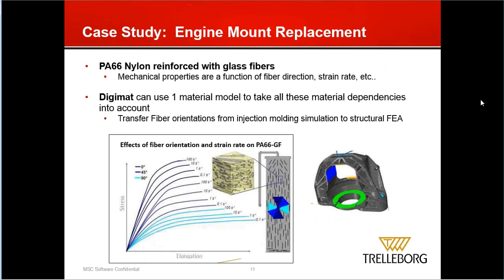The material they chose for that analysis is a PA66 nylon reinforced with glass fibers. And you can see from the chart below that this is quite a complex material to deal with. From the three different colors of curves, or three different groups of curves, you see that the material has a variety of stiffnesses and strengths depending on what the local fiber orientation is. In addition, you can see from inside each one of those groups that the faster you pull on that material, the more stiff it's going to behave, which means that it has a strain rate dependence. So this is a relatively complex material to deal with, and so they decided to use Digimat in the design process in order to take all of those things into consideration at once.